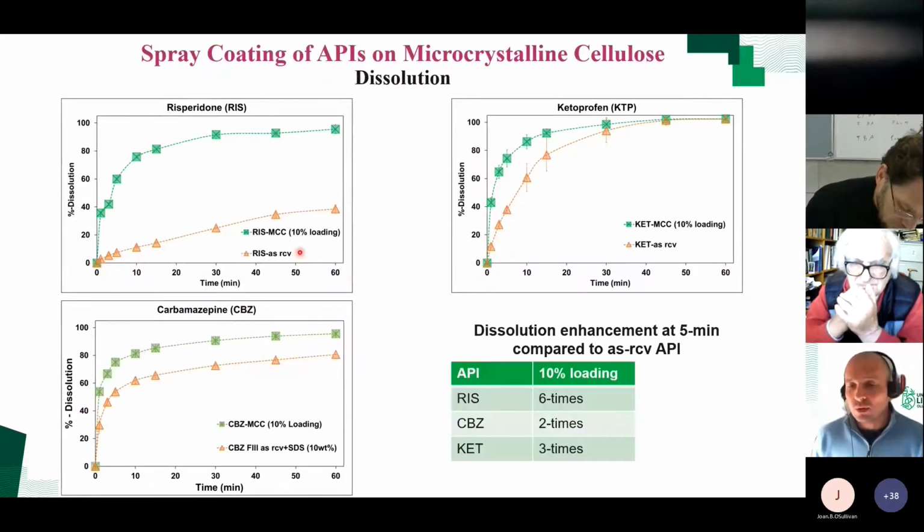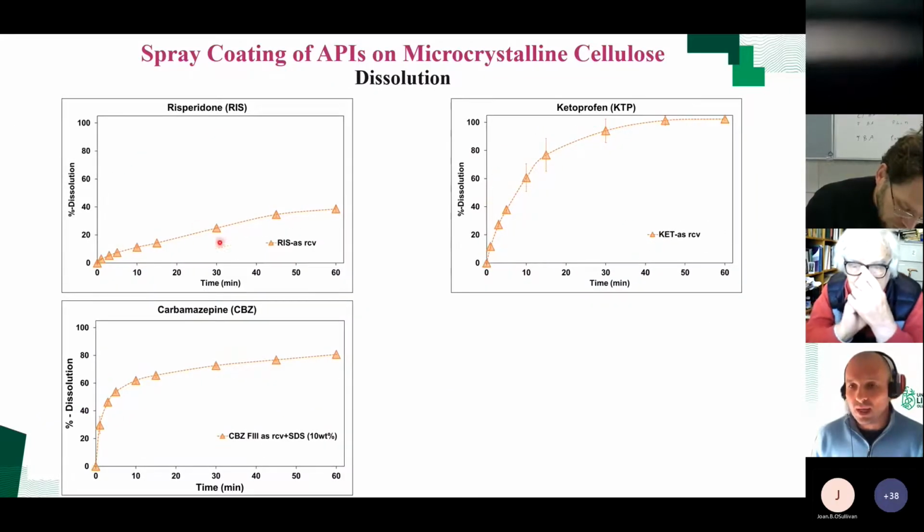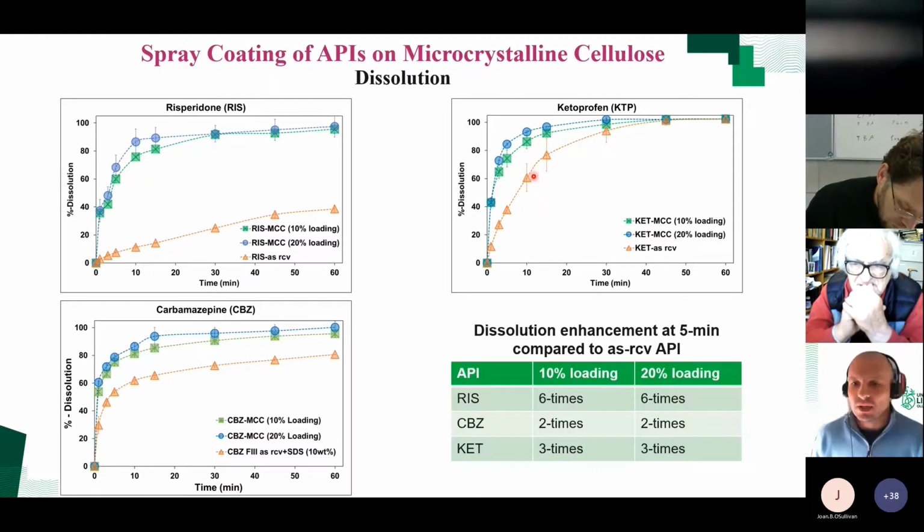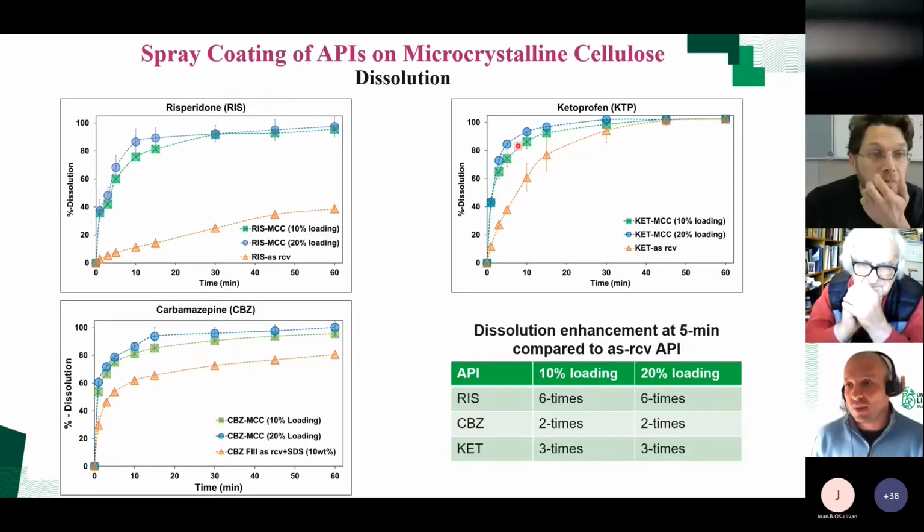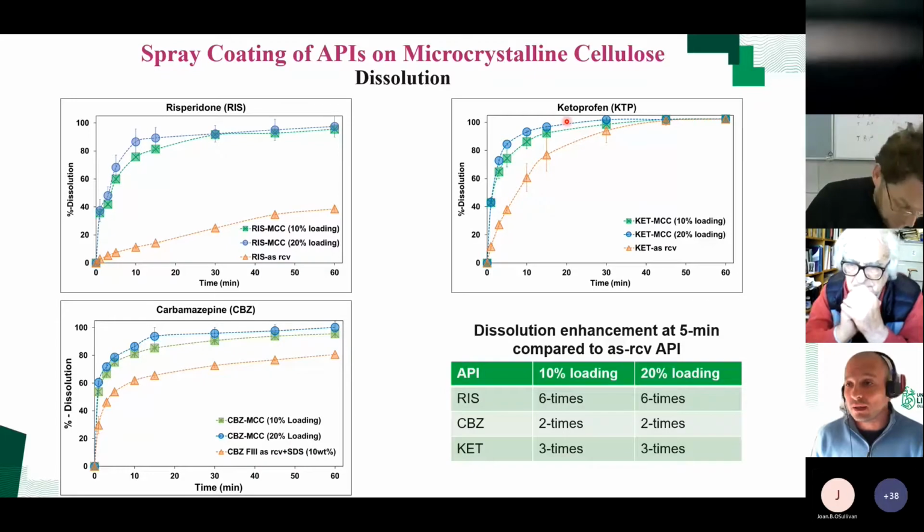They also have very good dissolution rates. The raw API has a very slow dissolution rate, but our formulations, although they are micron-size, still have nanoparticles of API there, and they dissolve very quickly.